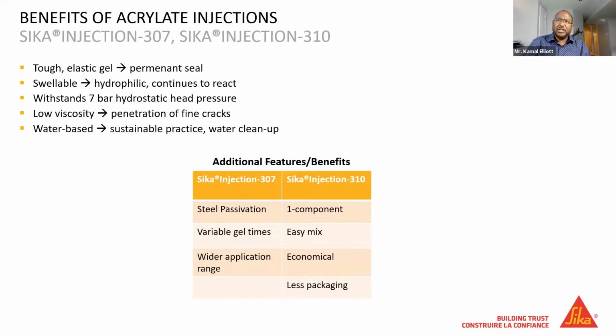So most of what we call hydrophobic polyurethanes, they cure once and that's it. They don't expand anymore in the future. But with these acrylic materials, they're what we call hydrophilic, so they will expand as water becomes present in the future. So they're really effective when it comes to withstanding water under pressure. We reference here a 7-bar hydrostatic head pressure resistance, which equates to 70 meters of hydrostatic head height. So quite substantial. And then viscosity wise, they're very, very thin. They're similar to water, more like a milk viscosity, which allows it to go where water would go. So very thin, enables it to penetrate into fine cracks.